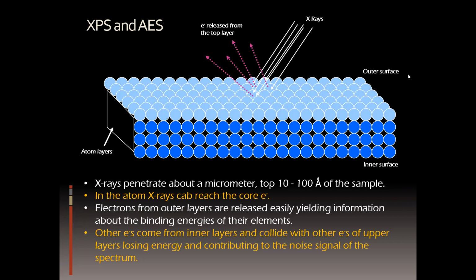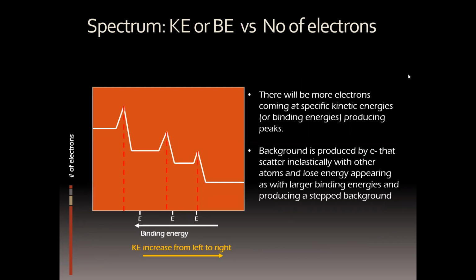The valence electrons or the core electrons. They can kick out any of those, but the ones that we're interested in are the ones in the core, which are more easily identifiable. And the rest are going to give you just noise over the other electrons. So if you count the electrons as a function of the kinetic energy that they have when they come out, you're going to see that there is a bunch of electrons that come out at some specific kinetic energy, and then nothing happens, and then there are some more, and then some more. The peaks correspond to the core electrons that you're extracting from the material.